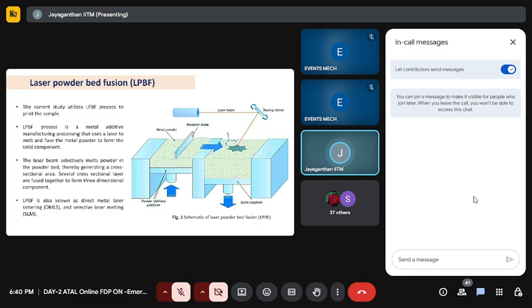We are using a thin layer of powder, scanning it with the laser. It undergoes instantaneous melting and solidification. As a result, going through the process layer by layer, we end up getting the final shape of the component. As I mentioned, if you want to build a new prototype, first I have to establish the material you want to print, and we have to qualify the powder first.